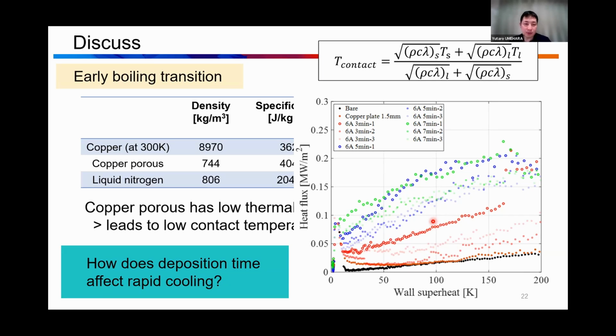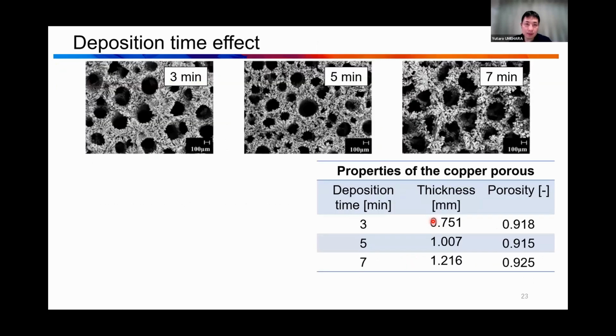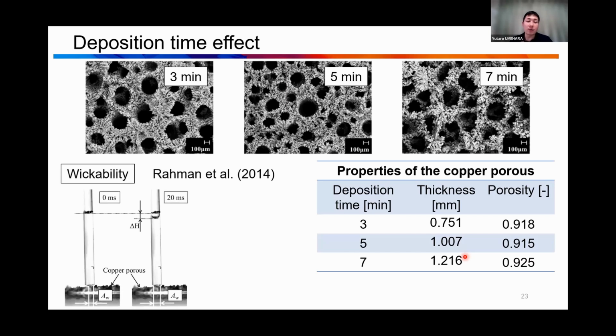So the next question: how does deposition time affect the rapid cooling? This is the same image, with different deposition times. The pore size changes a little bit, and the thickness also changes a little bit. So maybe various surface conditions also change, but we focus on the wickability of the surface. So we measure the wickability. When we attach a capillary tube to the surface, the liquid level changes due to the capillary force of the copper foam. We measured this speed and time change, and then finally we get this wickability value.